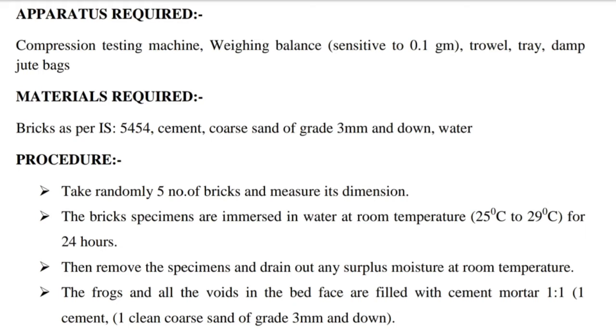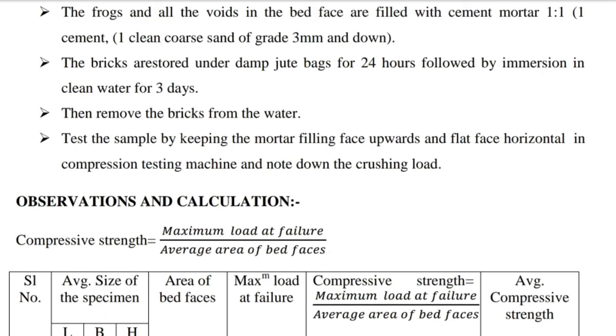Next, the brick specimens are immersed in water at room temperature 25°C to 29°C for 24 hours. Then remove the specimens and drain out any surplus moisture at room temperature. Next, all the frogs and voids in the bed face are filled with cement mortar in ratio 1:1 — 1 part cement and 1 part clean coarse sand of grade 3 mm and down. Next, the bricks are stored under damp jute bags for 24 hours followed by immersion in clean water for 3 days.